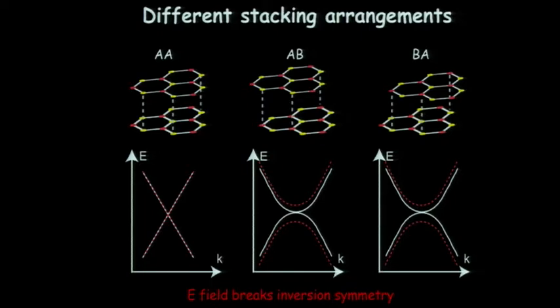And so in our measurements, we're going to have all of these different regions in the sample, and they're just going to be spatially separated. And we're going to apply an electric field from the tip and the backgate voltage. So we have our sample, we apply a voltage on the tip, a voltage on the backgate, that's going to apply an electric field. In Bernal stacked graphene, when you apply an electric field, you open a band gap.